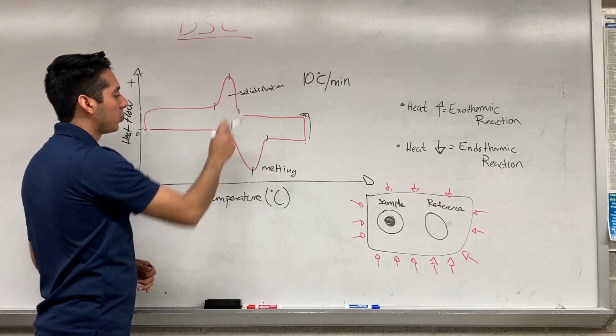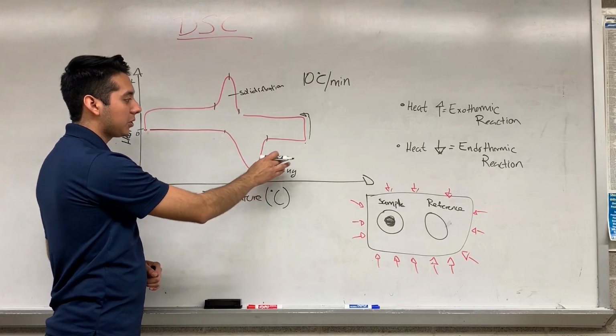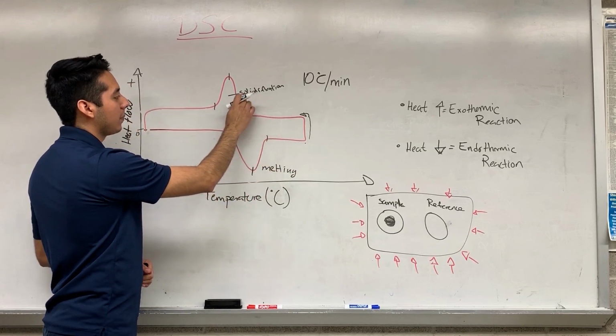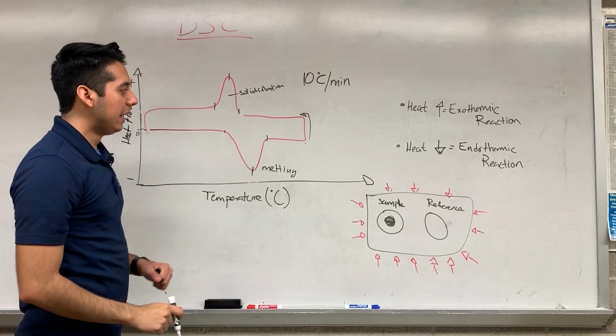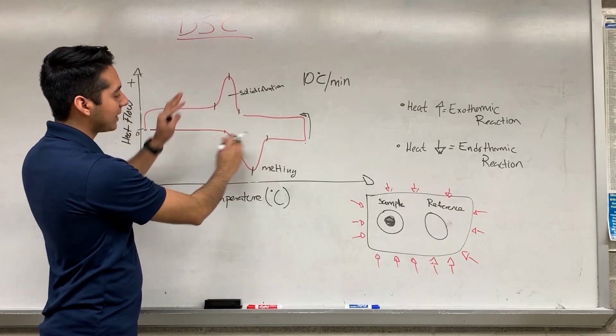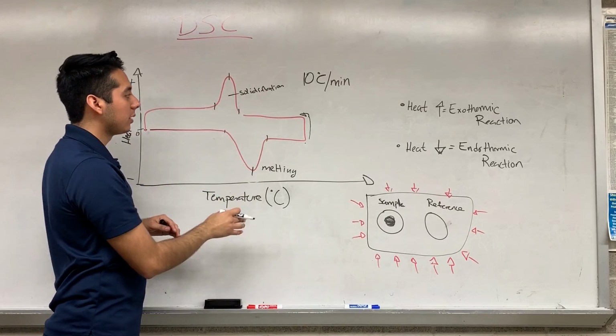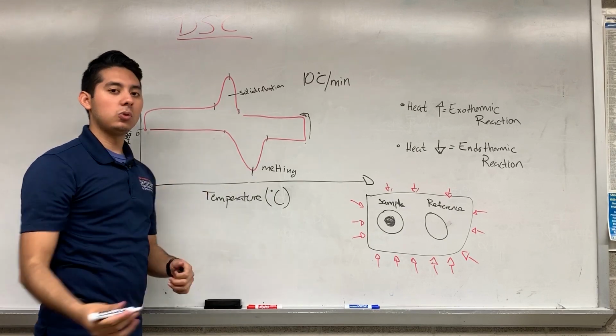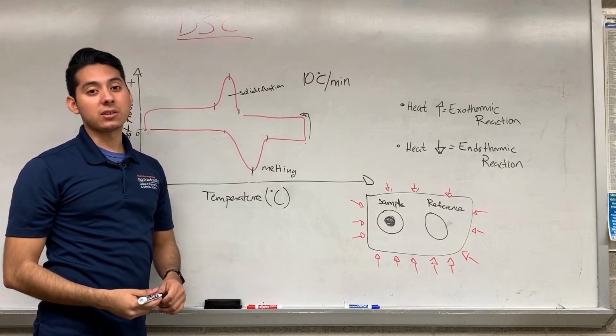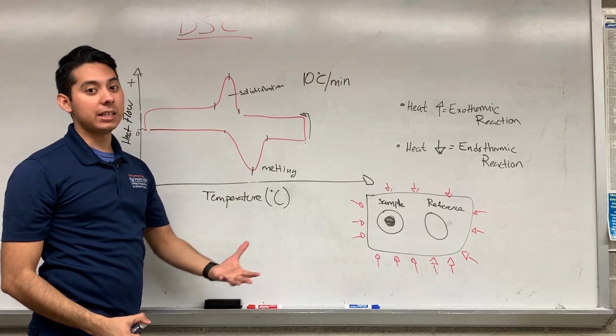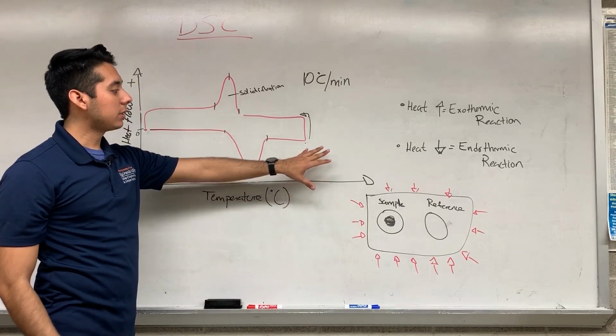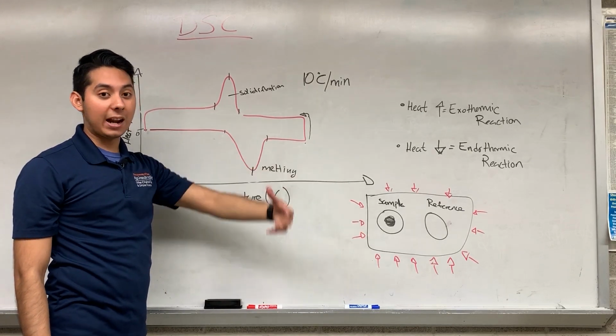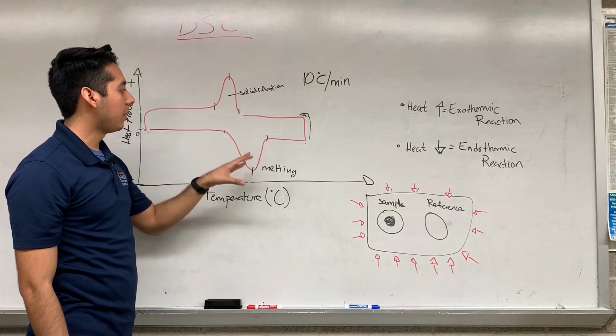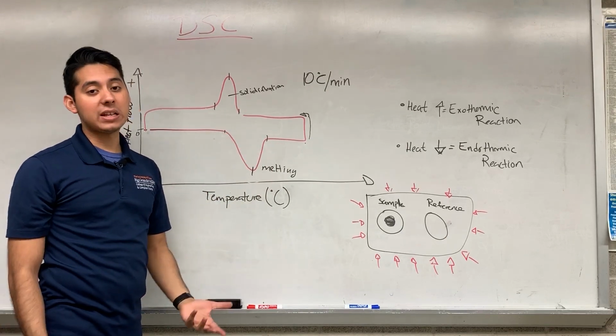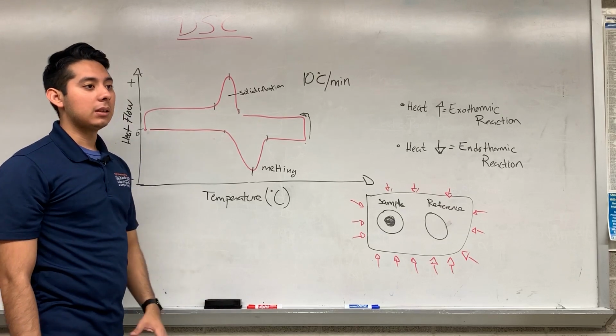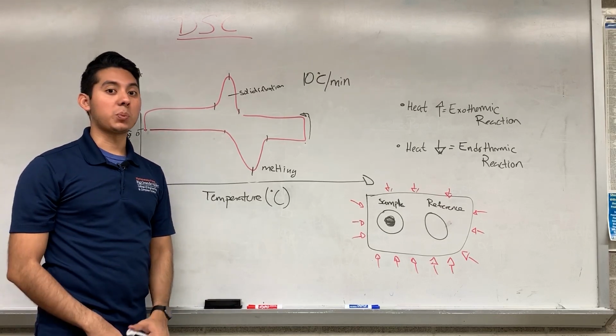Looking at these 2 peaks, we can find out at what temperature our material melted and at what temperature it solidified. As you can see, these 2 peaks are kind of shifted. They're not really on top of each other. They're not really aligned. That has to do with the dynamic effects of cooling and heating at high rates. When they do this test for alloys, to find out their melting and solidification peaks for the binary phase diagram, they usually do a rate of around 10 Celsius per minute.